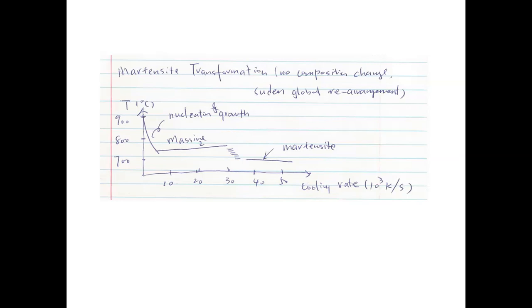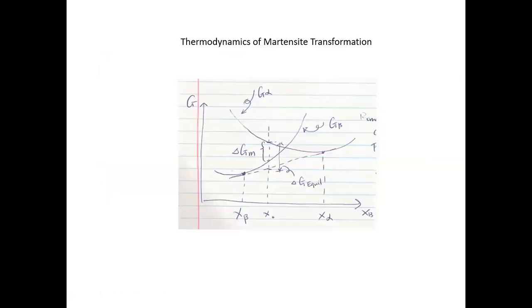Okay, so basically the martensitic transformation involves no compositional change. It's a sudden global rearrangement of all the atoms and change of crystal structure. Now, again, this is a sketch of the transformation pathway as a function of the cooling rate. If you cool very slowly, you're going to have nucleation and growth. You may not get the best results for that, but it's very tolerable. But if you cool super fast, like 50,000 Kelvin per second, if you drop the temperature very quickly, you're able to produce the martensitic transformation. Now, the massive transformation means that you don't have a global martensite, but locally you have this mechanism happening. So this basically means that we have a very fast cooling rate.